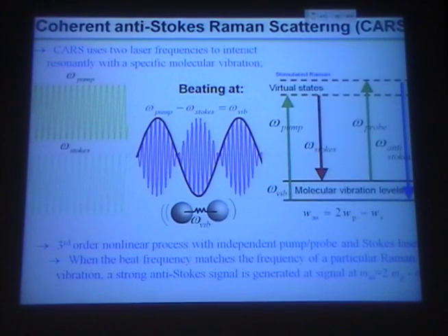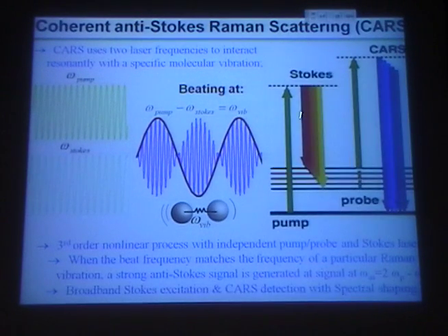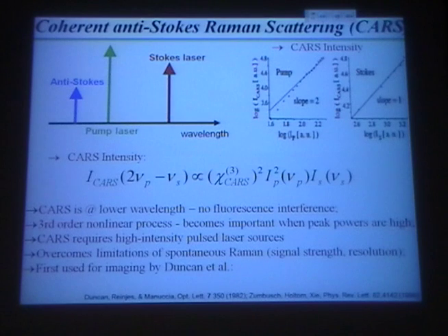Right, so now, in addition to simply using excitation laser light tuned to single frequencies and detecting information corresponding to individual chemical bonds, we can also do broadband coherent anti-Stokes Raman scattering imaging, because one can use a broadband Stokes signal, for example, as depicted here, and then we'll be detecting broadband coherent anti-Stokes Raman scattering signals, and this will contain information about orientations of not just one chemical bond of interest, but multiple different chemical bonds.